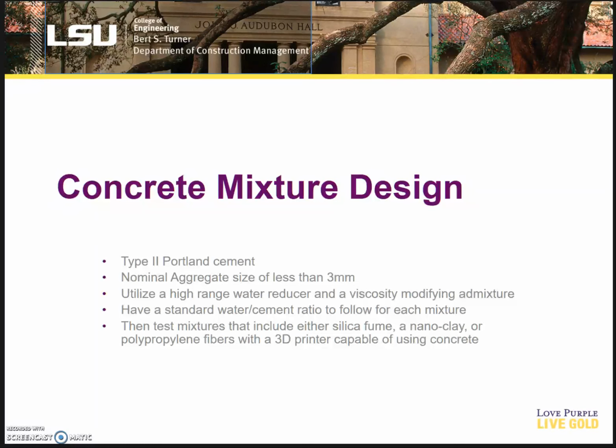Our cement and water ratio will have to be identical for each of our mixtures, which we're going to have 4 of total. And our 4 concretes we will be testing will be, as a control, 1 without any of these admixtures, 1 with silica fume, 1 with nanoclay, and 1 with polypropylene fibers. Each of these help increase cohesion for the mixture and increase strength, compressive strength for the concrete.